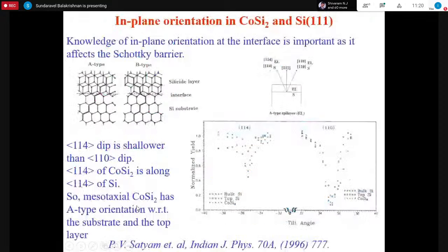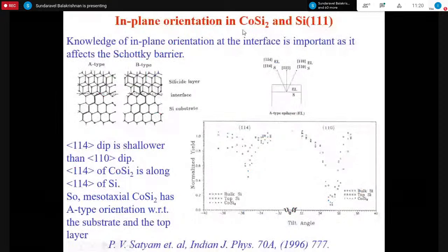And as such, if we take cobalt disilicide, we can determine what is the in-plane orientation of cobalt disilicide on the silicon substrate. Normally, if we grow cobalt disilicide by molecular beam epitaxy or some other deposition techniques, this cobalt disilicide orientation will be rotated 180 degrees from the substrate orientation. If it is rotated, it is called B-type cobalt disilicide. If it is not rotated, it is A-type cobalt disilicide. When we make it with ion beam synthesis, we observe that it is A-type cobalt disilicide, where there is no rotation.